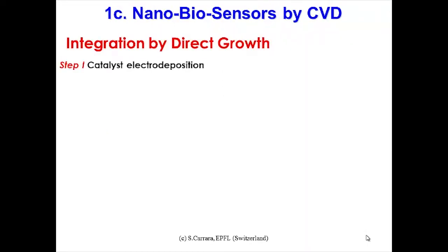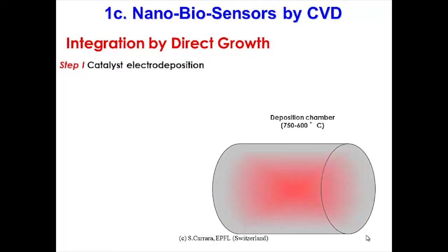But the best results we obtained by using chemical vapor deposition. Some of you who are more aware of it know that it is very well known. We can grow carbon nanotubes both on semiconductors and on metals. The only problem is that they grow everywhere. So if you design a multi-panel platform and you have, I don't know, a platinum electrode and nitride or oxide passivation, at the end of the growth you obtain carbon nanotubes everywhere. So it was a bit painful for the poor PhD student working on this task, but she is very smart and at the end succeeded in getting exactly what she wanted: carbon nanotubes only on the sensor and not shortcutting one sensor with another.